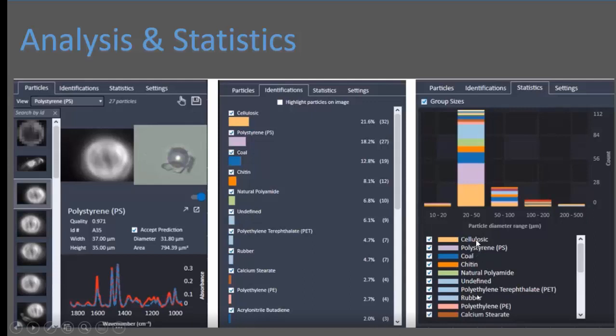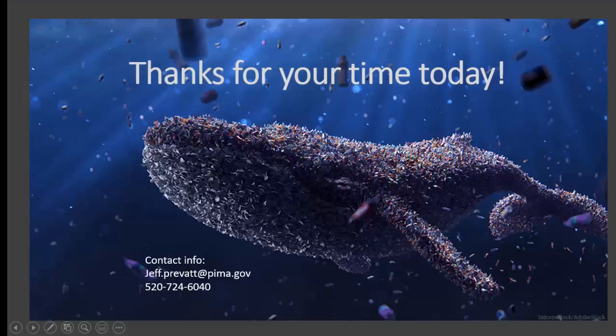We still have cellulose on screen because we know we're dealing with wastewater matrices, so we look for that. But here's some normal sample analysis, and it tells you what the particle size range was for each of those particles. For this wastewater influent, we'll see that almost 95% of all of our particles are in the 20 to 50 micron range, with the second tier being in the 50 to 100 micron range. Very valuable information we're able to acquire.